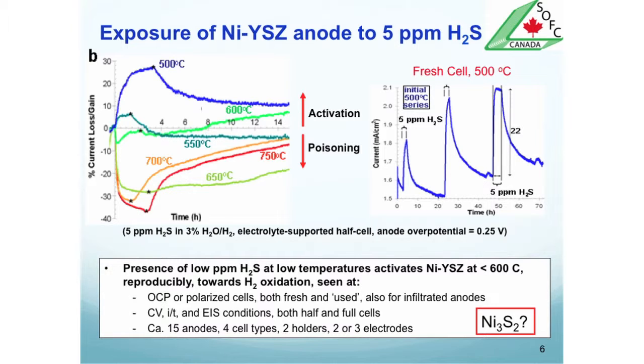But what was so interesting to us, and we've seen it now time and time again, is that as we move to the lower temperatures, 600, 550, 500, that would be what you would encounter if you wanted to go to a metal-supported SOC, for example, our Theme 3A goal. And of course, many people in the literature are trying to go to still lower temperatures. What we saw over and over again is that we'd introduce H2S, and the current would go up, not down. And when we removed H2S, we lost activity. So I know many of you heard this earlier from me, but indeed, we see that over and over again.